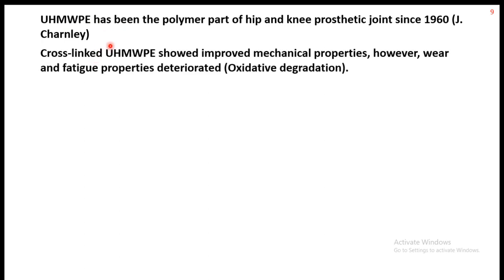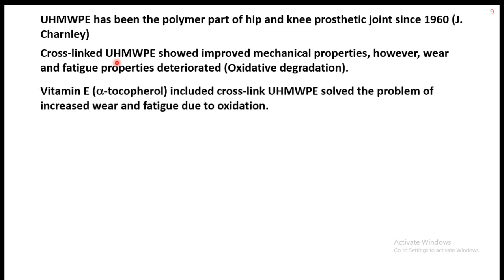But later it was further improved by cross-linking. So cross-linked UHMWPE showed improved mechanical properties. However, wear and fatigue properties deteriorated because of oxidative degradation. Because cross-linking in UHMWPE using gamma irradiation produced many radicals, and that led to oxidation of UHMWPE.